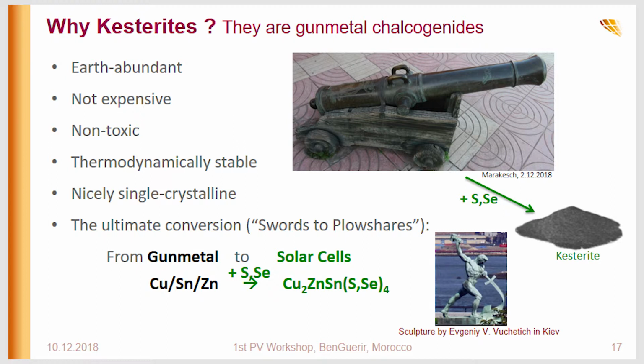And coming from the peace movement, in which I worked for quite some time, it's quite nice that this is actually the ultimate conversion, because the combination of metals, copper, zinc, and tin, was called gunmetal, because this is where the guns were made from. This is a gun in Marrakesh, actually, made from this material, and we convert this gunmetal to solar cells, just by making the sulfides and selenides.